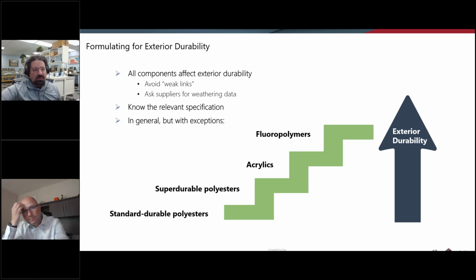And so acrylics, the reasons that they're not used as much in architectural coatings, a couple of reasons. One, they are excellent for very high gloss, smooth, and especially clear coat type of coatings. They fit perfectly into the automotive segment because when you want that high gloss Class A finish, you can get that with an acrylic powder coating.